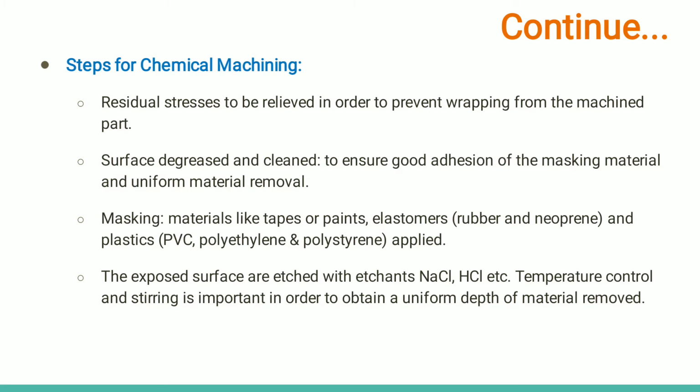Then temperature control and the stirring action are important to obtain a uniform depth of material removal. If the chemical continuously flows inside the container, then whatever temperature rise occurs should be uniform throughout. That means the temperature rise of the chemical solution inside the container will be uniform, and that causes a uniform depth of removal of the material. So these are the steps that we have to follow.